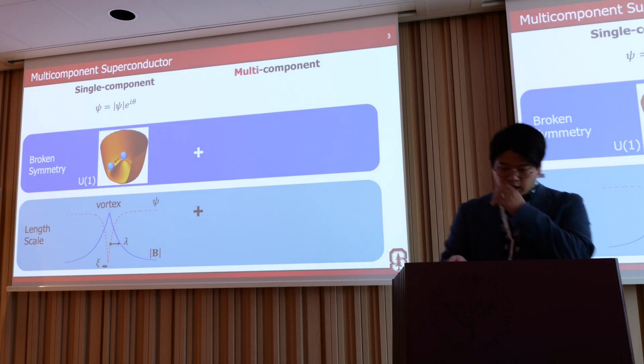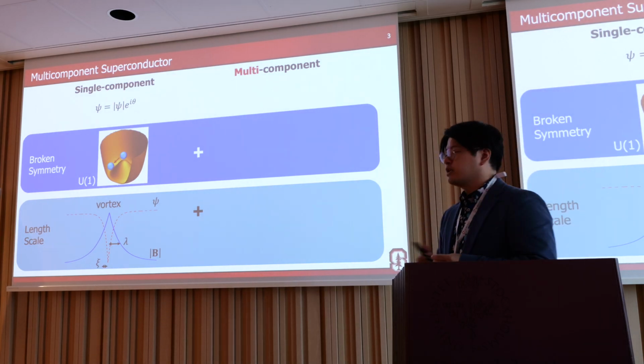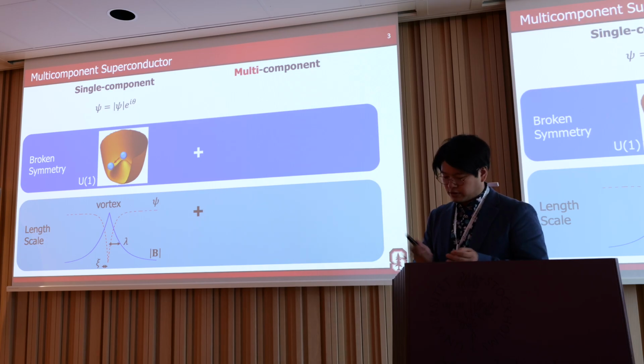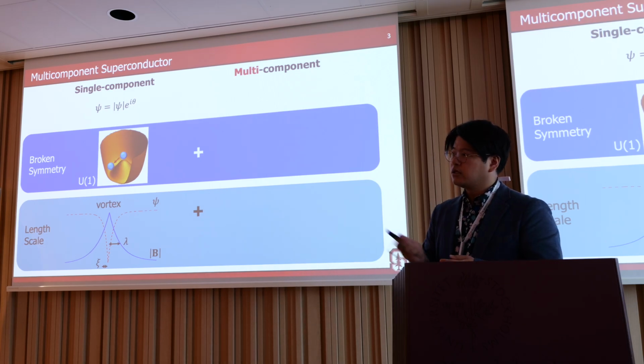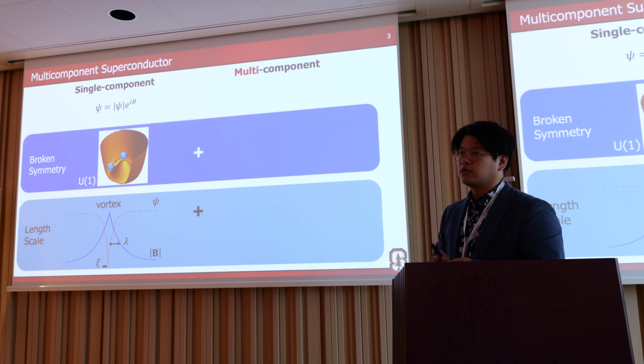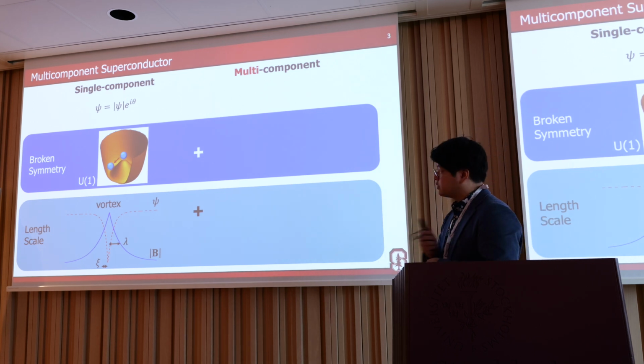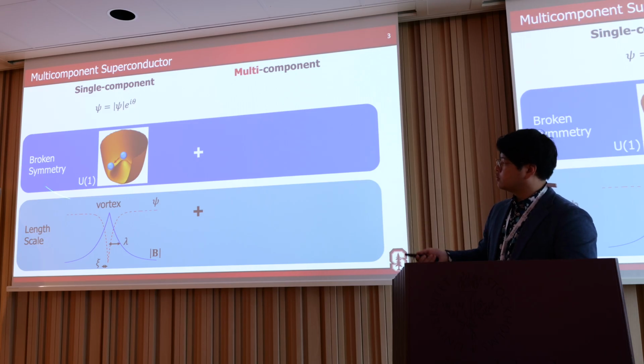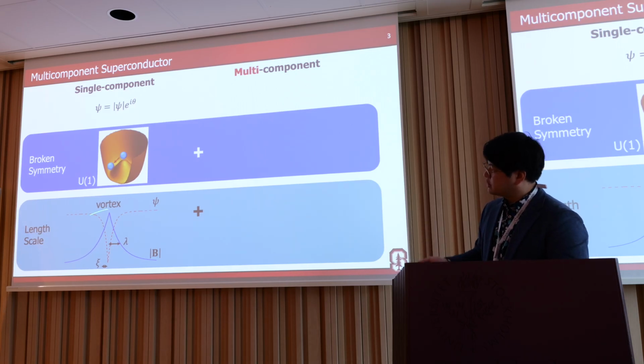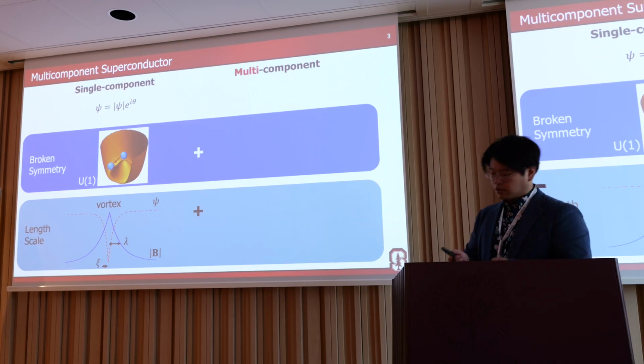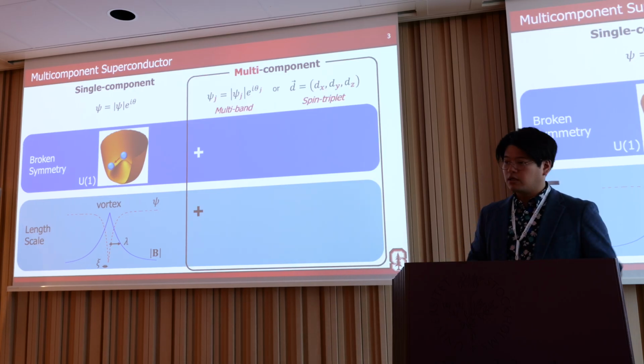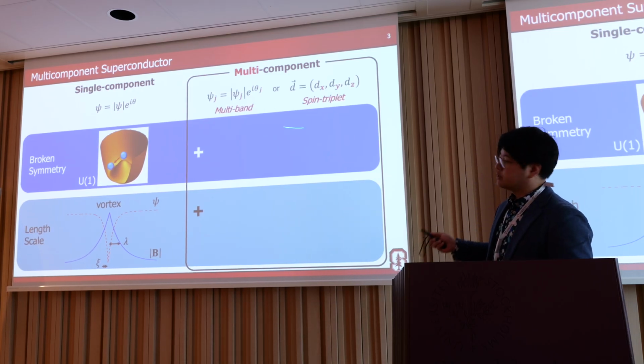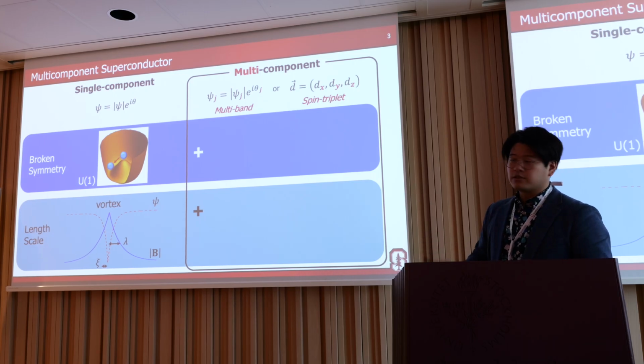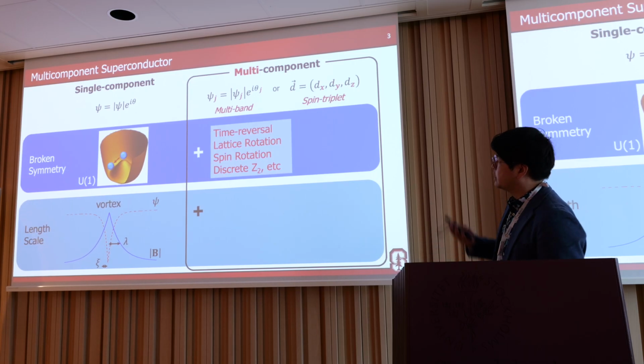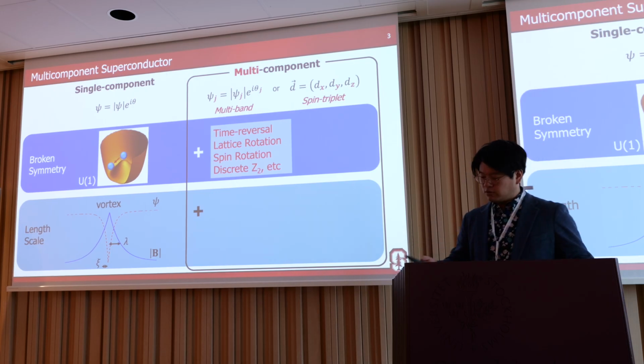Okay, so my talk is about multicomponent superconductors. For a single component superconductor, as you know, there is the broken U(1) symmetry and two characteristic lengths: penetration depth and coherence length. For the multicomponent, it's more complicated because of the multicomponent order parameter, like multiband or spin triplet, and then additional broken symmetries, like time reversal symmetry, lattice rotation, spin rotation, Z2.